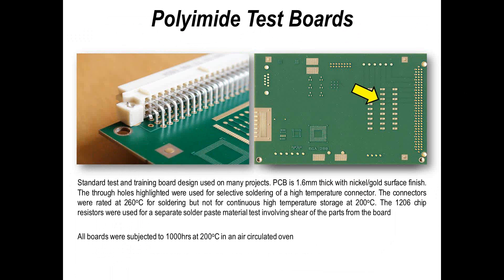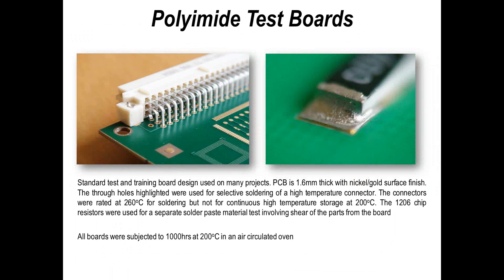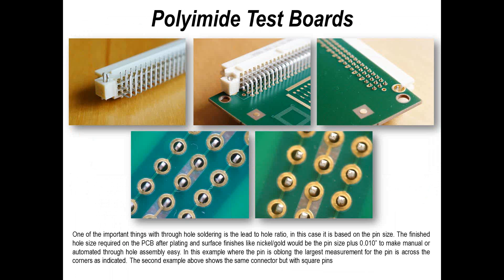I use this connector for intrusive reflow, through-hole wave solder, and selective soldering all the time. The connector design rules are the standard rules I use for pretty much anything I do. The hole-to-lead ratio is based on the pin size: maximum pin size plus ten thousandths of an inch gives you the finished hole size. This is perfect for wave soldering, selective, hand soldering, and intrusive reflow.